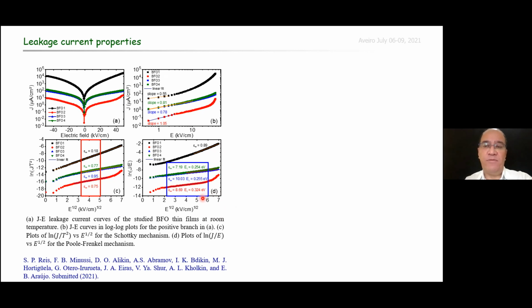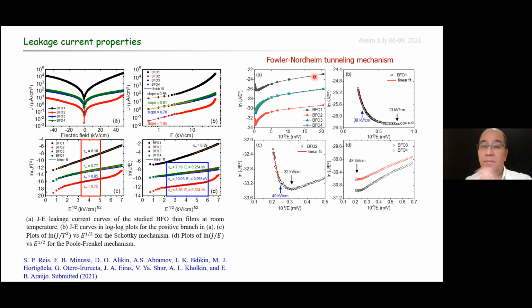Finally, we also check for the possible Fowler-Nordheim mechanism as summarized in this figure. This mechanism was discarded for both BFO3 and BFO4 films, as indicated in this figure. However, for the BFO film with bismuth in excess, the BFO1 sample, and for the bismuth deficient, the BFO2 sample, this mechanism is possible at high electric fields.